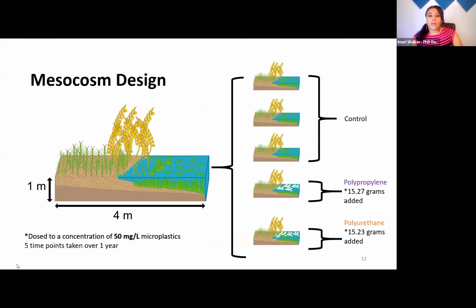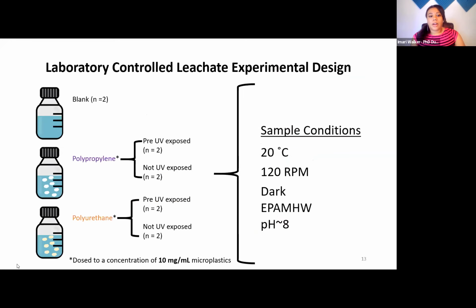So the mesocosms are actually in the Duke Forest, and they're 12 feet long, 3 feet deep, and they have just about everything in them from water, plants, sediment, snails, and anything else that wants to jump in from the forest. But these boxes were dosed with both polypropylene and polyurethane in each individual box, and water samples were taken over 1 year. To complement this study, I also did an in-house laboratory controlled leaching experiment for about 3 months. And within the same plastic, I also pre-exposed it to UV light to age the microplastics ahead of time.